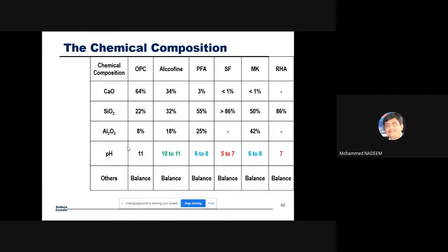These are the chemical compositions of these materials. Along with OPC, you have alkofine, fly ash, silica fume, metakaolin, and rice husk. Most of the materials are silica; silica fume is majority, about 86% silica. Metakaolin is a combination of silica and alumina. Alkofine is a combination of both. It has cementitious properties towards the OPC. So you have silica, alumina, and calcium oxide.